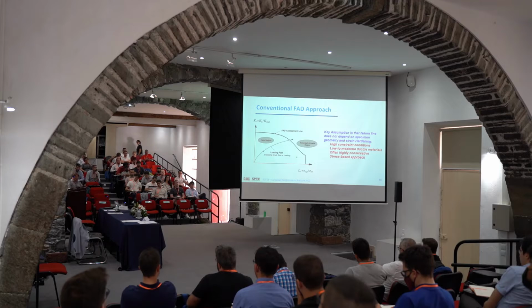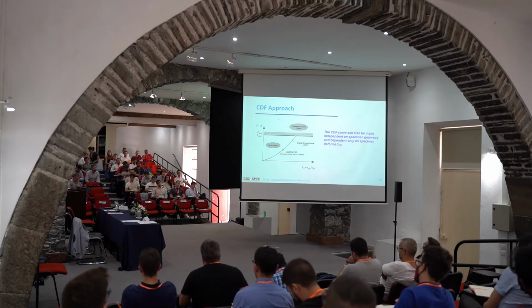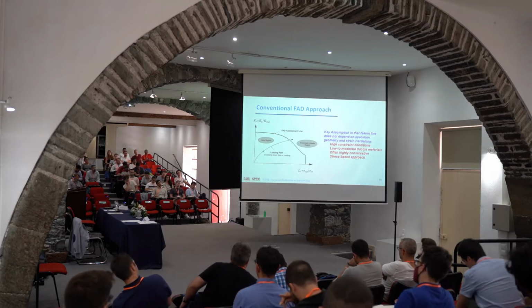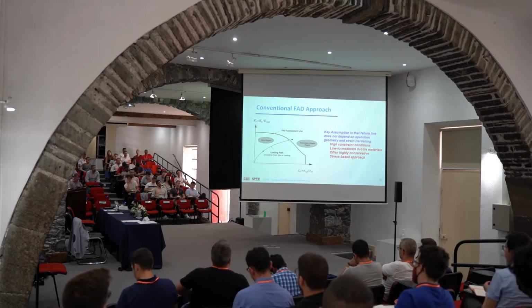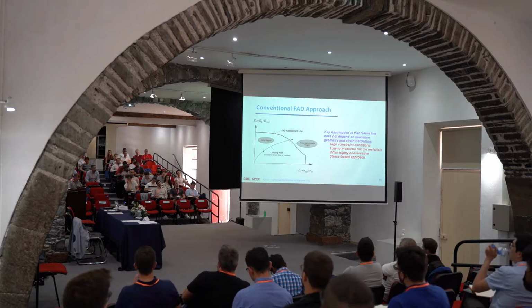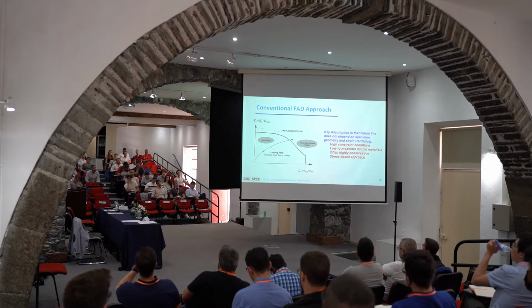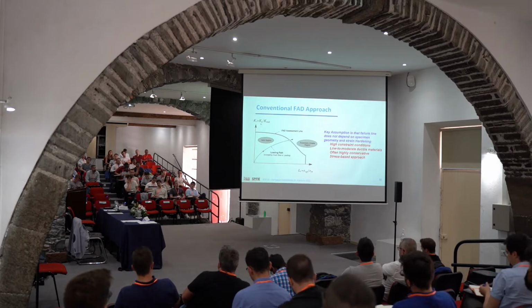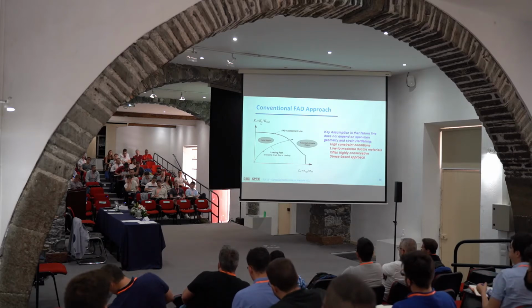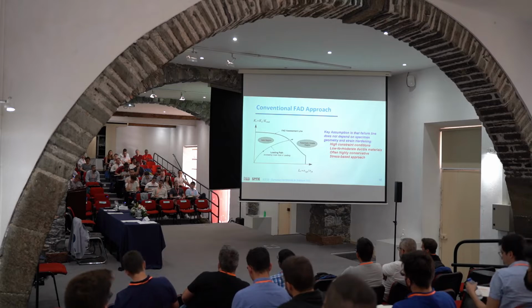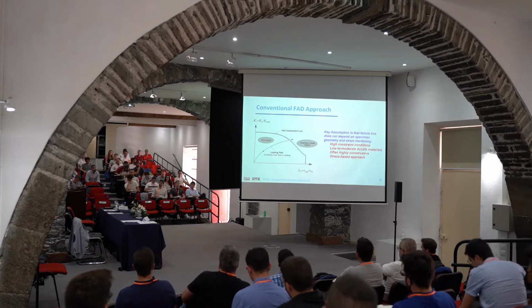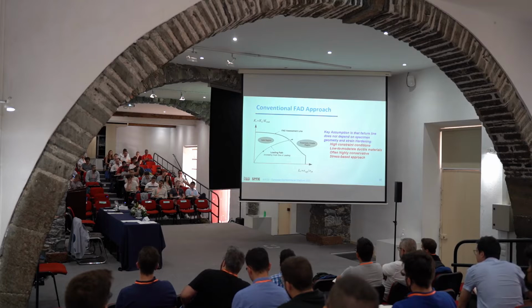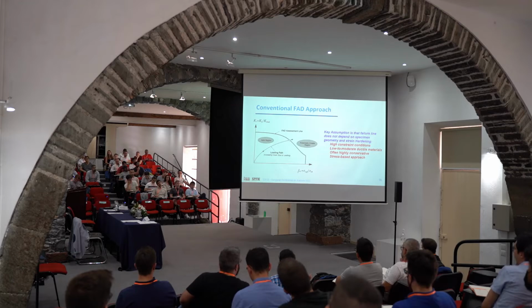That's the idea. And the other nice thing about the failure assessment diagram approach is that it is actually a two-parameter approach. It is a combination of fracture, as you all know from the fracture mechanics course, where the driving force has to be less than the toughness, and also the plastic collapse.